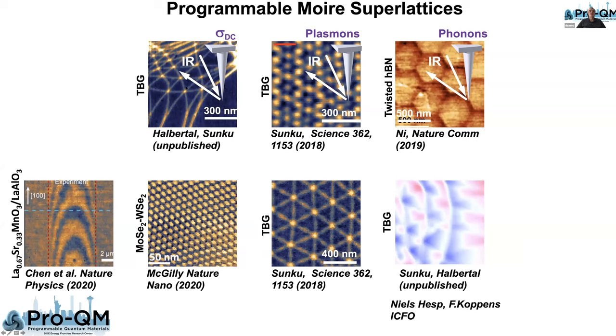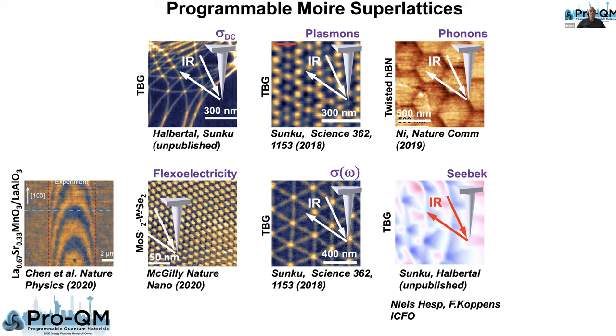This technique was invented by Frank Koppens and Rainer Hillenbrand in Spain, and we extensively utilize it. You can set up this experiment slightly differently, and you also record local maps of local Seebeck coefficient, so you can even record thermal properties. I talked about local conductivity already. In semiconducting van der Waals materials, it's useful to be able to obtain flexoelectric contrast that is a counterpart. This is the only non-optical measurement in this map, but flexoelectricity is related and complementary to our measurements of local lattice dynamics.